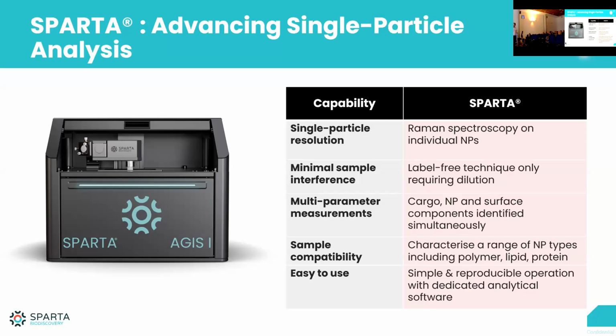We want to use a label-free technique, ideally. With SPARTA, you only need to dilute your sample. We don't need to add anything to get the standard signal out of the particles. That's really important. We also look at the native state of particles in solution. Just your vial with your particle, whatever the particle might be, we can put under the machine in liquid state. So we don't have to dry the sample, we don't have to adhere it to a surface or things like that. We can just look at the particles directly in their native state.